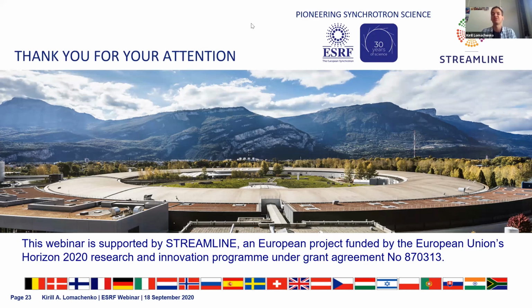If you work in an unfocused mode, like you do for chemistry most often, we don't foresee significant problems with radiation damage unless your samples are super sensitive, and I guess yours aren't. However, this will be a big issue at ID24 DCM, and we are ready to face it. We'll have to be very careful with the attenuators of the beam, attenuating it for each particular experiment depending on the nature of the samples, as little as possible, but enough that the beam does not alter our samples and does not alter the chemistry we are studying, which is even trickier than not hurting the samples themselves. Thank you.